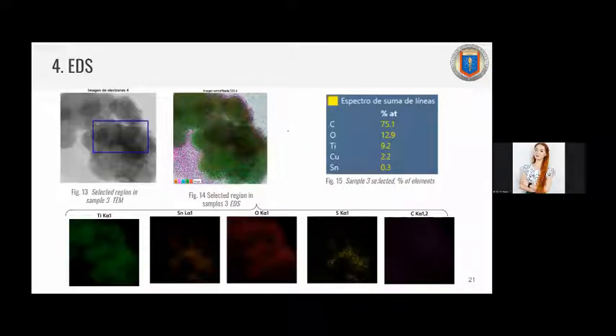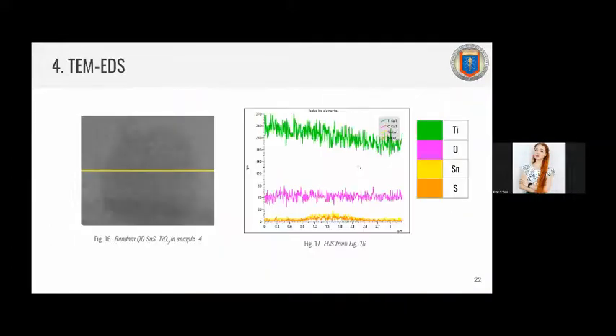And here's an example of the EDS of a selected region in one of the samples, and the percent of elements that we obtained. And we could see that we have titanium dioxide and tin sulfide elements as well. When doing the EDS in the TEM, there was also another qualitative verification. We can see also the different elements that we had, titanium dioxide and tin sulfide also present, with tin sulfide, the quantum dots, in much less amount, of course, than the titanium dioxide.